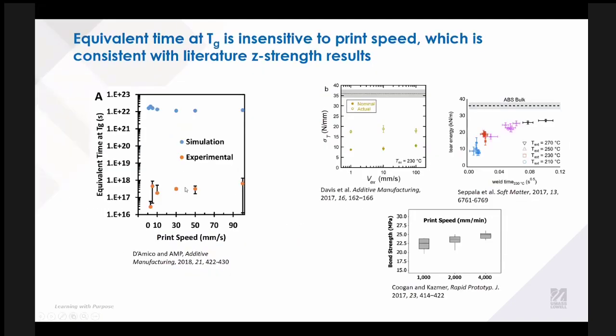And so that's why we're seeing that lack of sensitivity to print speed, and that leads, in a number of cases, to print speed independent tear energies. And in fact, what we end up seeing is that extruder temperature, the temperature that you set your hot end to, is far more important for the strength of your part. So all of these individual colors represent a single extruder temperature over a range of print speeds, and they all kind of collapse onto one another.